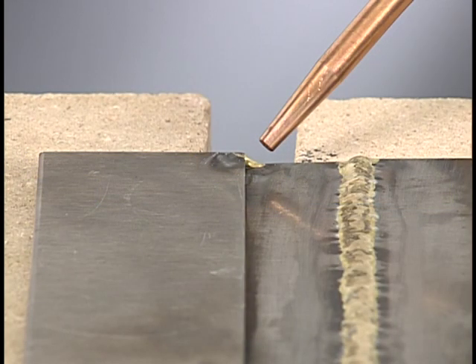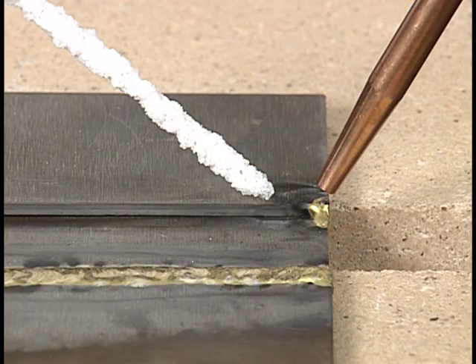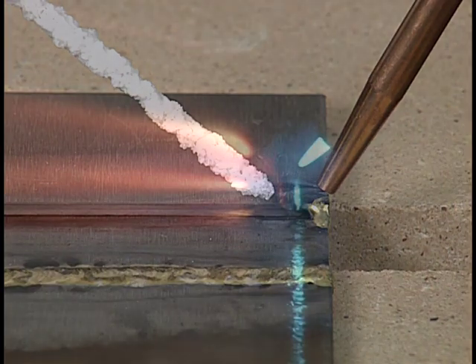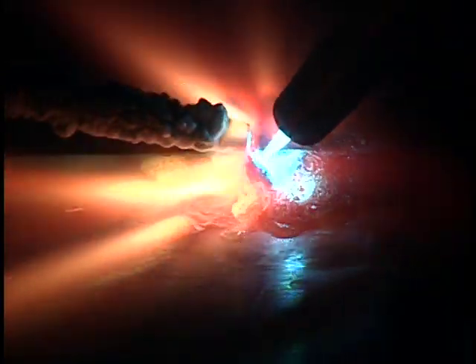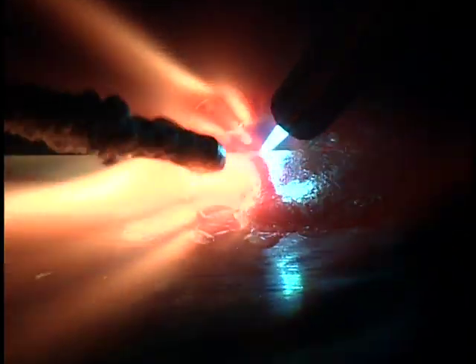Position the torch with a work angle that is approximately 45 degrees. Use a 25 to 30 degree push travel angle. The filler rod will be held over the axis of the joint at approximately a 45 degree angle. Hold the torch in position, and when the metal becomes dull red in color, touch the rod to that spot on the metal to melt a little flux and filler. Once again, be careful that you do not melt the base metal.